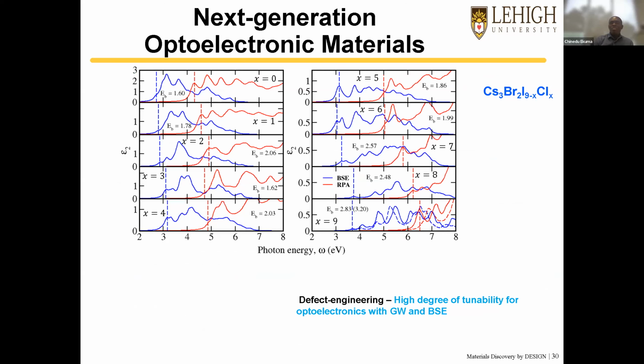We recently started doing some isoelectronic substitution in these materials, and we are seeing something even more interesting. This material has one of the highest exciton binding energies ever known. It's almost 2.5 eV. I mean 2.5, sorry. The binding energy is almost of the order of 2.5 eV, which is one of the largest, if not the largest, known for any 2D systems out there.